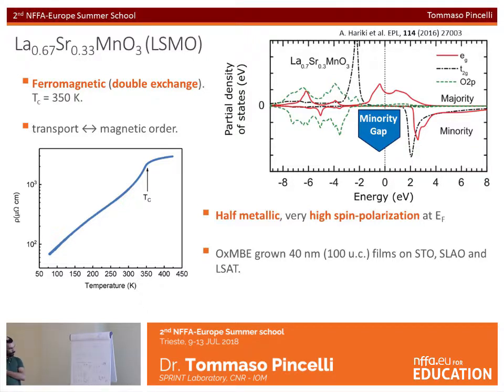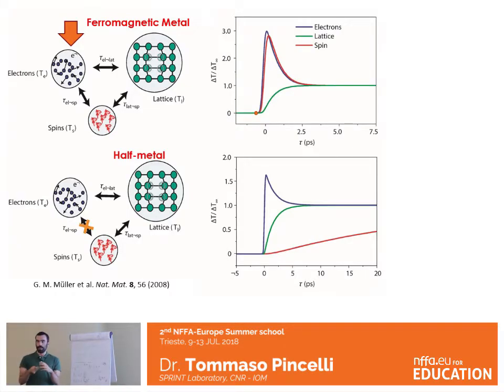So let's go back to the picture that I showed you in the beginning of the different sets of excitation processes that we can trigger. In a magnetic material such as this, we have 3 sets of possible excitation that we can trigger by exciting with a short laser pulse. So let's start with a simple ferromagnetic metal. We excite the charge, the kinetic energy of the charges, the vibration of the lattice, and the order of the spin, the magnetic order. So if we excite the kinetic energy of the electrons, then we produce optical vertical transitions, and we increase suddenly the temperature of the electrons.